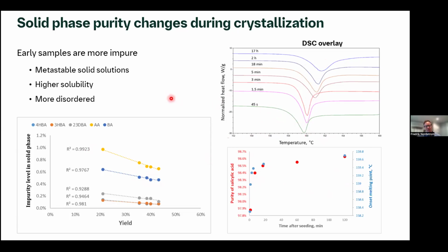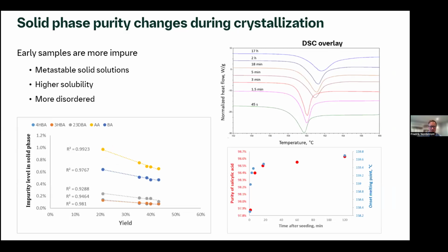So what this means is that we are creating metastable solid solutions early on, and they slowly approach equilibrium as you're crystallizing out. And this early metastable solid solution phase, because it's higher in impurity load, that means they also have a higher solubility initially. So the concept of supersaturation changes when you're working with solid solutions. You can't say that the supersaturation is this as you're starting the crystallization. It depends on the solid phase composition. And also that you're getting more disordered material in the beginning, right? So that speaks to the non-classical nucleation theories.